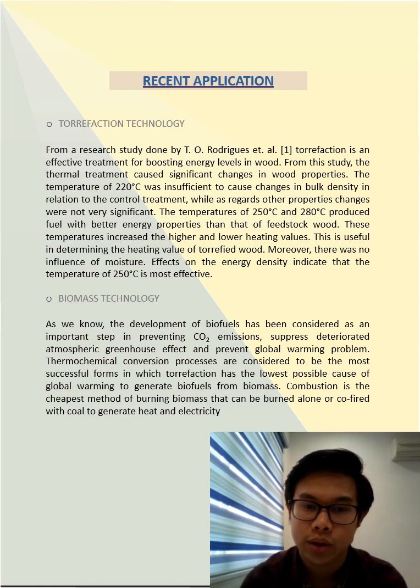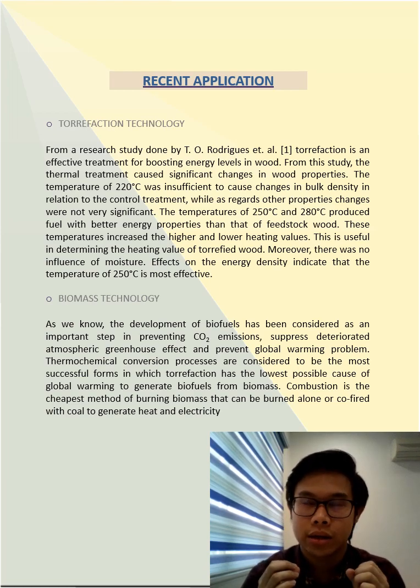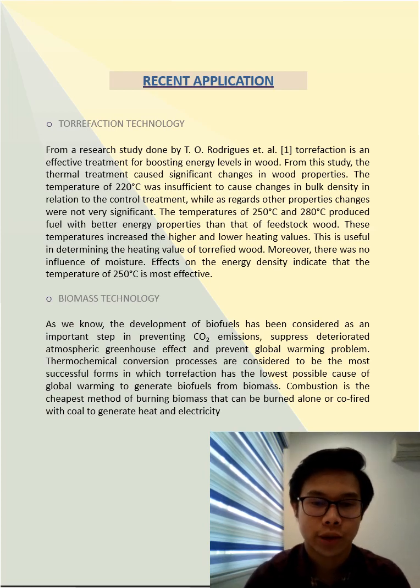Moreover, there was no influence of moisture. Effects on the energy density indicate that the temperature of 250 degrees Celsius is the most effective temperature, which means 250 degrees C is the most optimum temperature in yielding high energy. For the next point, biomass technology.